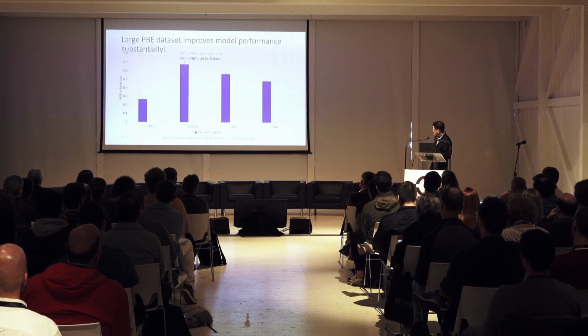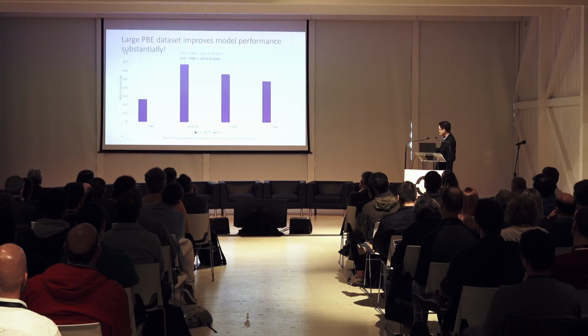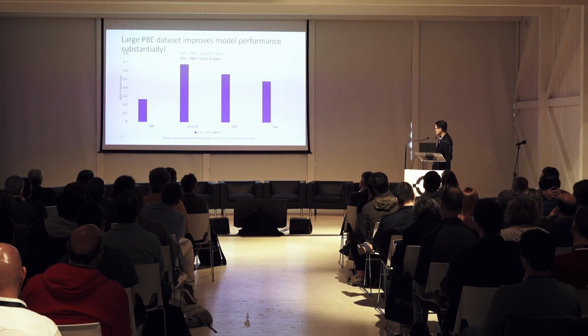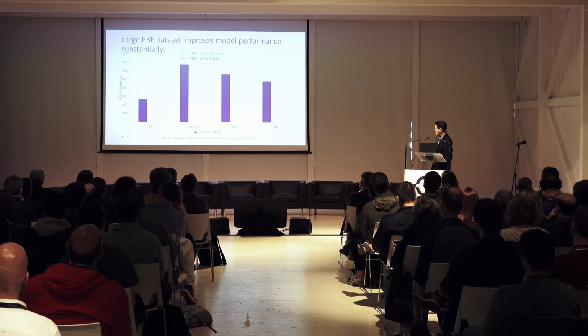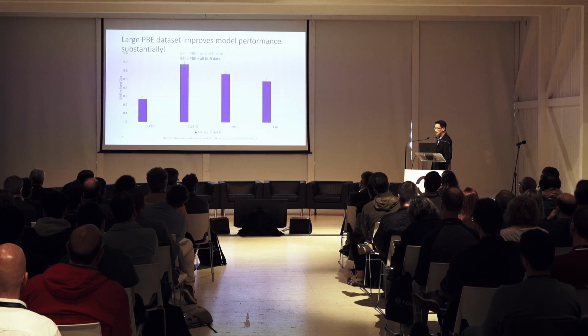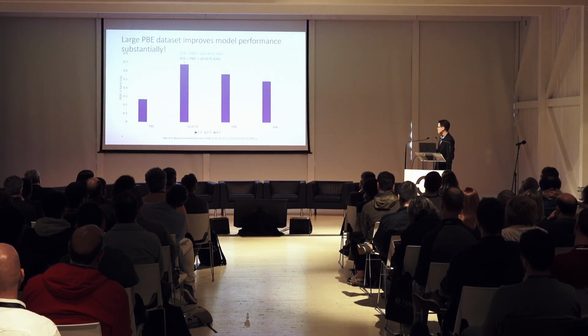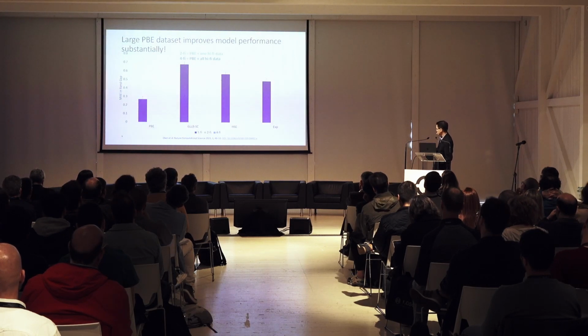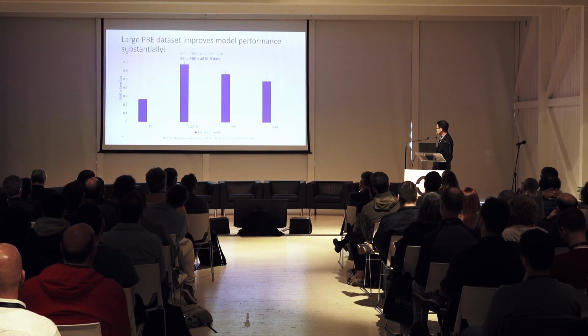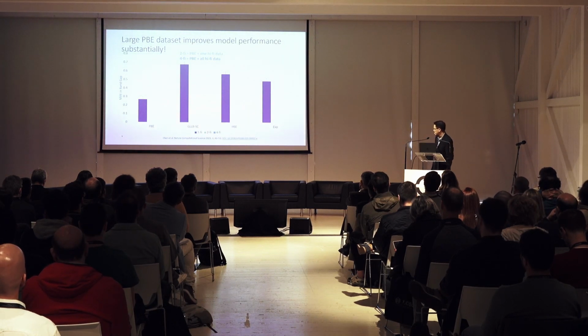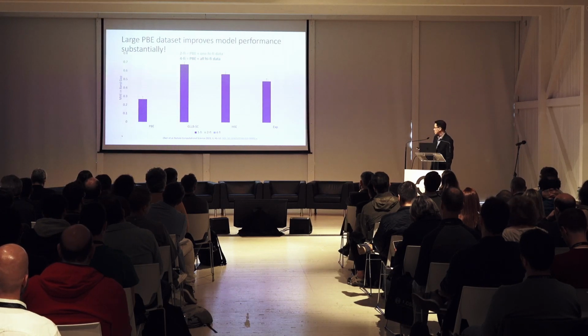Okay? Now, just to show you that it works, this is what happens. This is the error in the band gap if you build a model using each of these data sets in turn. So the PBE data set is the biggest, which is why the error in the band gap is also the smallest. Okay, so we can make very, very good predictions of very inaccurate PBE band gap data. Okay, so the error is about 0.3 eV or so. However, the error in the HSE and experimental band gaps are almost double that of what you get with PBE, right? Because the data set sizes are a lot smaller.